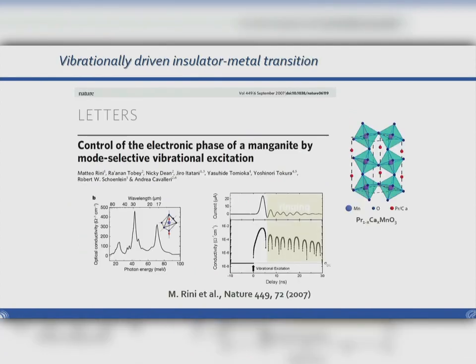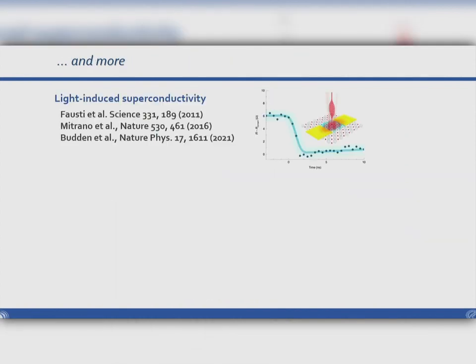And indeed, the very first demonstration of such a vibrational-driven control of functionality was done in 2007 by Andrea Cavalleri when he was still in Berkeley. So tuning a mid-infrared excitation pulse into resonance with a certain phonon of a manganite induced an ultra-fast insulator metal transition, which was probed here via electrical transport. But we can do a lot more with this.